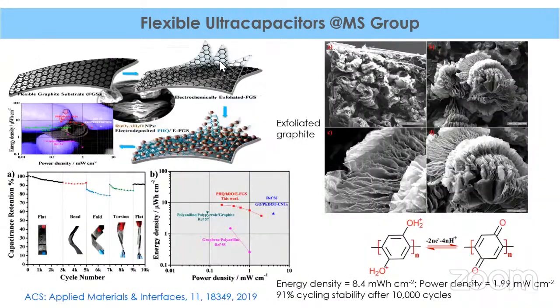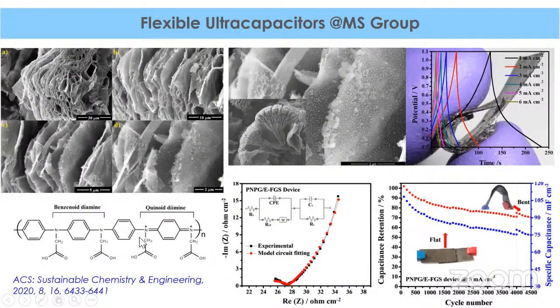So the same flexible exfoliated graphene substrate he has used for coating another polymer system. Here you can see, instead of polyhydroquinone, he has used poly N-phenyl glycine, call it PNPG, which is again a pseudocapacitive conjugated conducting polymer. So it was also synthesized by the electrooxidative polymerization method. N-phenyl glycine is used as a monomer here, and that has been electrodeposited on these graphene sheets that are anchored